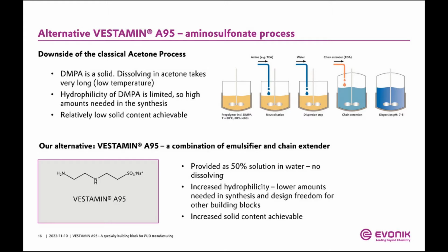You have an increased hydrophilicity, so that means the sulfonic acid salt is more hydrophilic than the DMPA or the DMPA salt. So that means you need either less of this material in your formulation or you achieve higher solid contents. So it is up to you which way you want to choose to take advantage of the system.